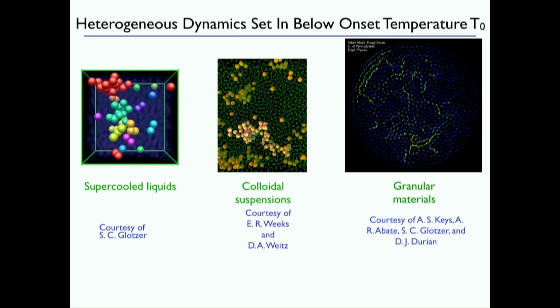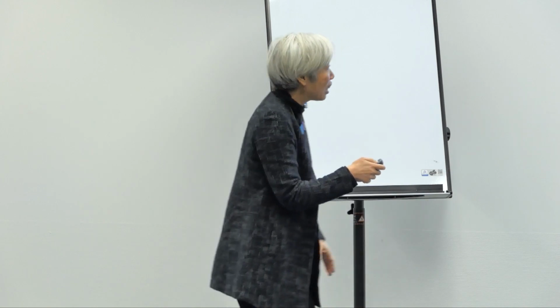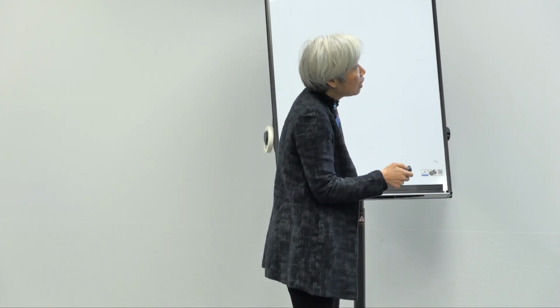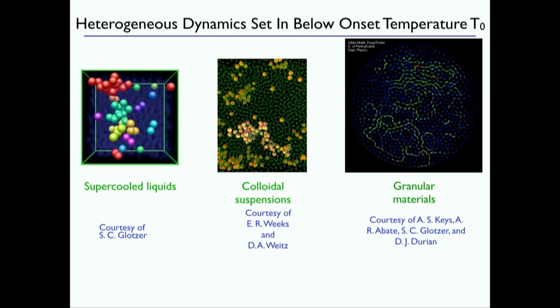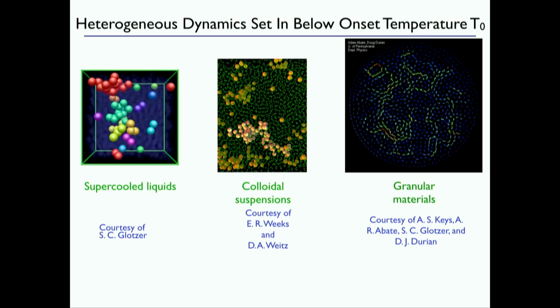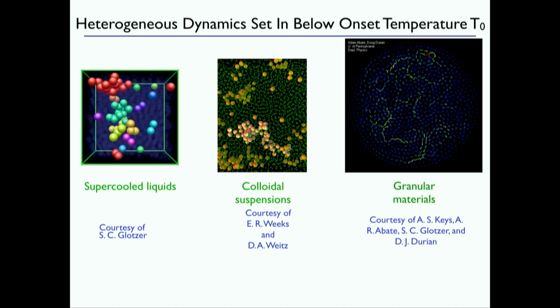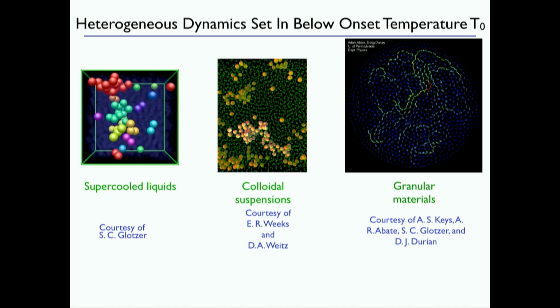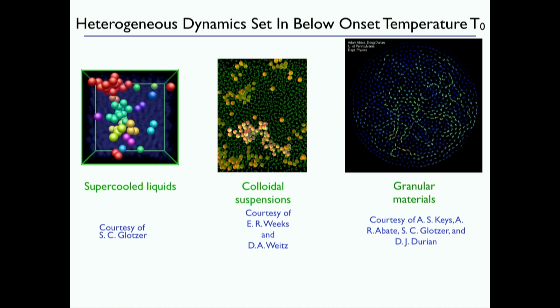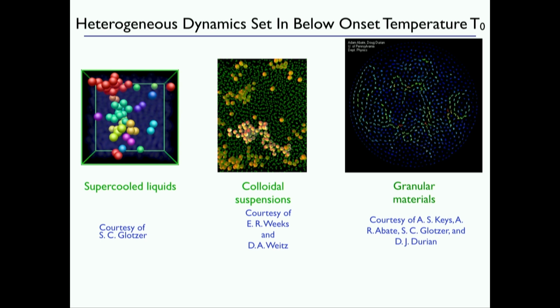This is actually a movie of a granular system. So this is a system of grains. They're on a wire mesh, so it's a two-dimensional system. They're sitting on a wire mesh, and gas is being blown. Turbulent gas is being blown through this, and because of the mesh it becomes turbulent, and the little eddies push the particles around, so they get excited, and at a high enough density, here's a movie of the particles, and they are colored according to how far they moved during the stress relaxation time, and you see that the blue ones didn't move very much, and the red ones moved the most. So you see that heterogeneity.